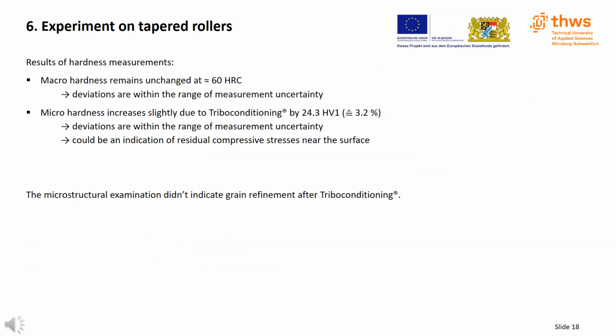Now to the hardness results. Regarding macro hardness, no change was observed due to triboconditioning. Both test groups have a hardness of approximately 60 HRC. Minimal deviations between the test groups are within the range of measurement uncertainty.